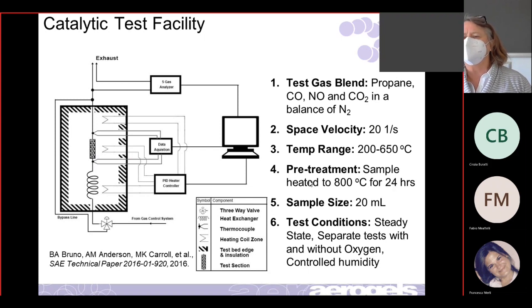Before we test a sample, we have to preheat it. When we just make it, we heat it to 800 because it changes, and it will change when we do the testing. So we preheat it ahead of time. We use about 20 milliliters of sample. One of the things we do is test with and without extra oxygen to mimic fuel-rich and fuel-lean. We have the ability to switch between them at about 1 hertz. We haven't done it yet, so we do them separately, with extra oxygen or with regular oxygen each time. You'll see some of my results.